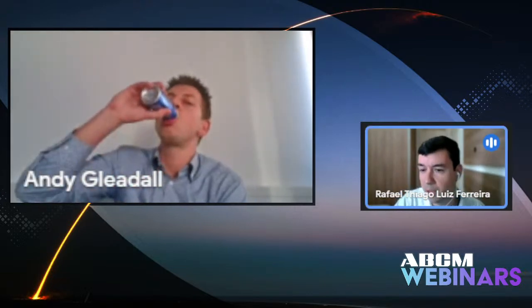Okay, cool. We usually think that there is also a role for material adhesion and things like that, but apparently for the cases you studied, the most important is geometry. Without doubt, the most important is geometry. The adhesion between materials does exist as an issue, but it is nowhere near, from our vast studies of single filaments, what the influence of geometry is.